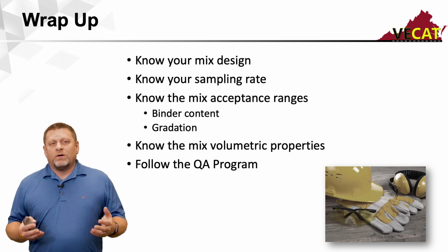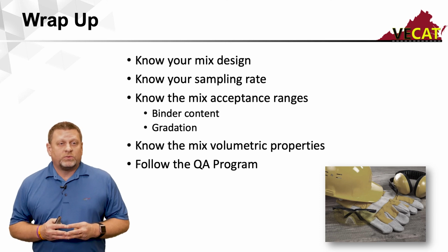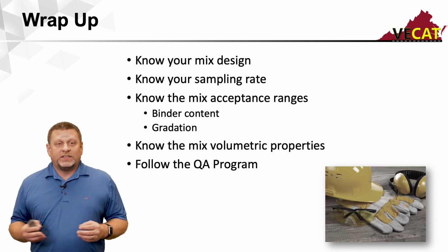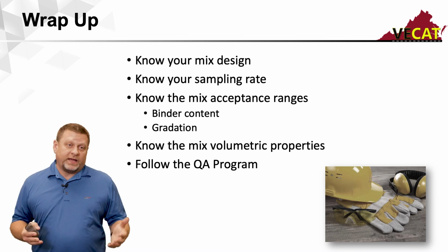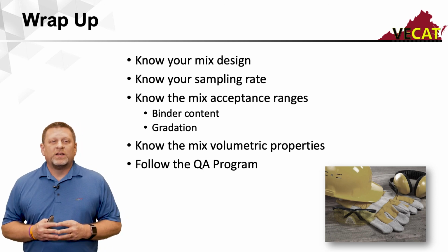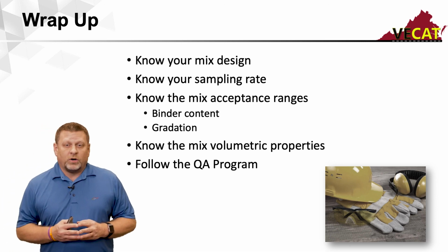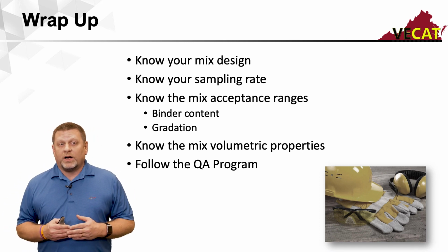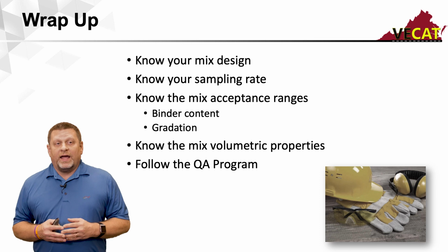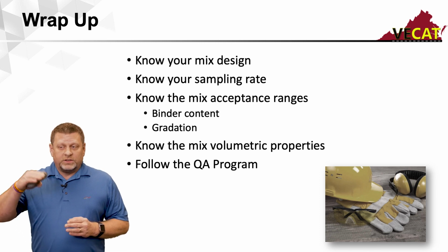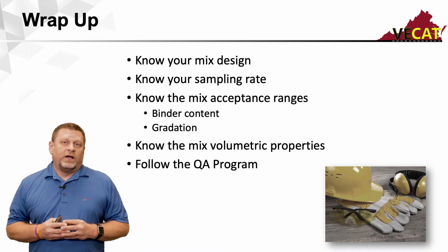And as we talked about before, your acceptance ranges, whether it be for your furnace burn, your binder content, or your gradation, you want to make sure that not just the spec sieves stay in tolerance, but all the sieves are staying within tolerance. I think we talked about some control charts previously. These are a really great visual resource to monitor your asphalt content and your gradations to make sure everything's staying constant. You don't want a whole bunch of peaks and valleys in the plots of these control charts.